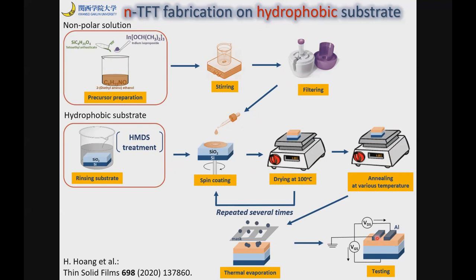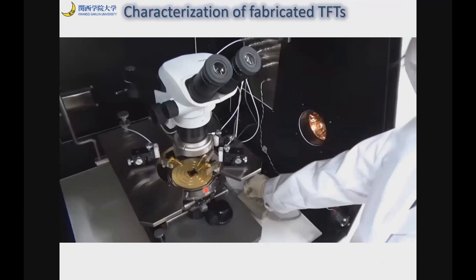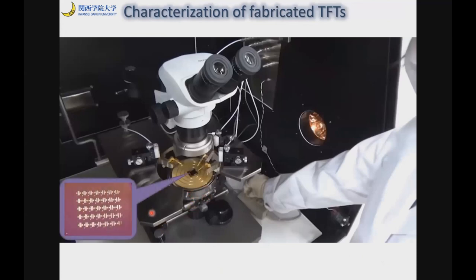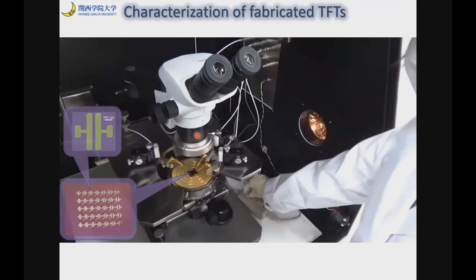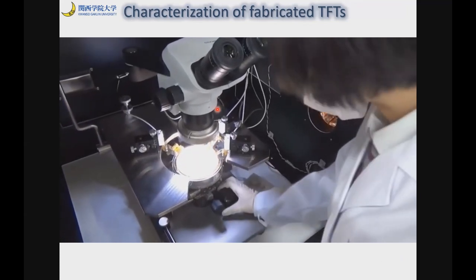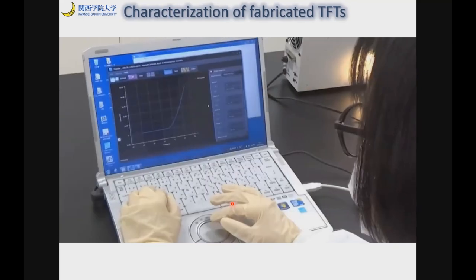In this case, two electrodes on the semiconductor films are evaporated by vacuum physical vapor deposition. So here is a physical vapor deposition system. We use a physical vapor deposition procedure. Okay, so please see the movie. Because our devices are very small, we cannot contact the electrodes by hand. Therefore, we use probers. Here are very small tips on the devices. Then we contact the probes under the microscope, and then measure the device performance.